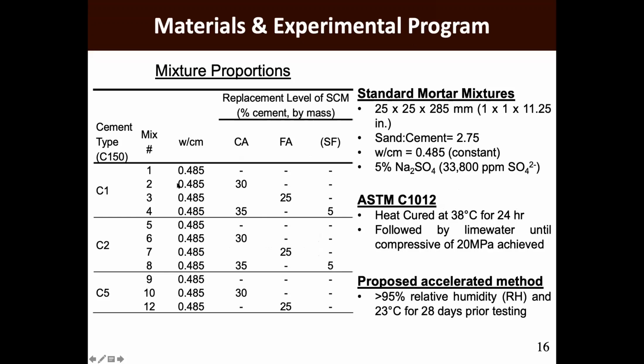The mixture designs were all based on the same C1012 methodology, 0.485. The Class C was a 30% replacement, Class F 25, and then the ternary system with a 35% Class C and a 5% silica fume. Again, this is for C1, C2, and C5 systems. And the only difference, again, is that we vacuum saturated the sample. So we looked at both C1012 as a control and the vacuum saturation system.